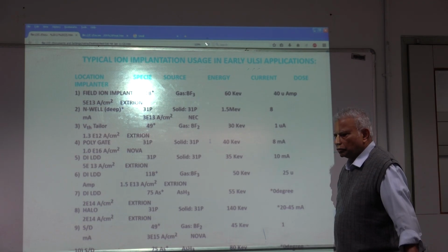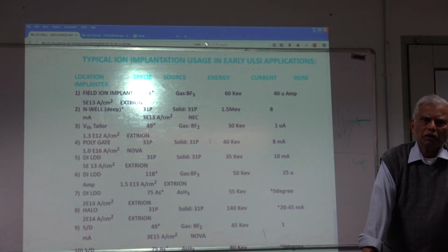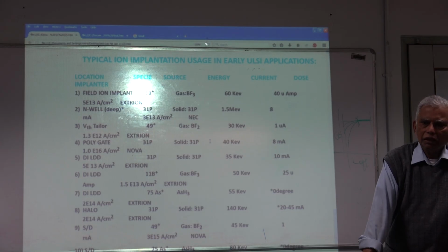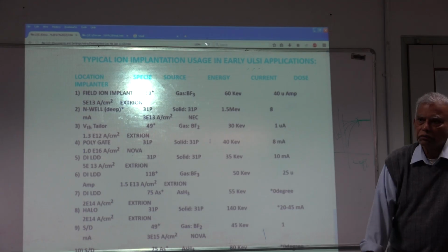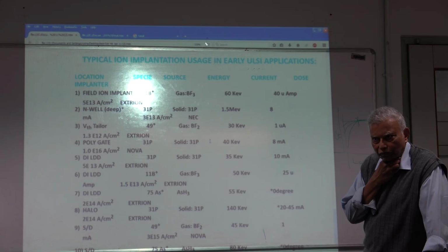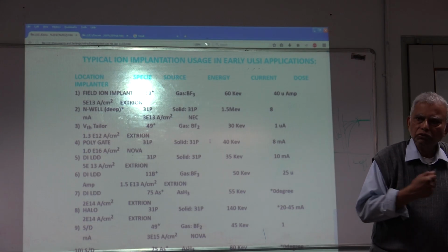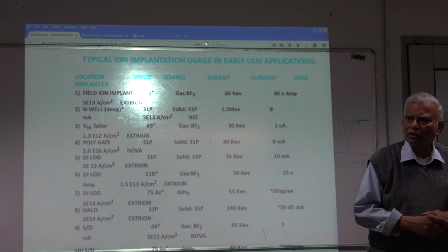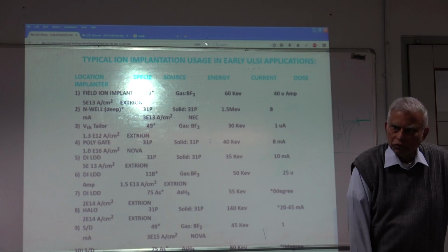So, for everything that I'll talk about with you tomorrow, assume we're using implant. We're no longer using the old way of doing diffusion. It's all implanted diffusion. And I will touch upon when you implant, especially when you implant with higher energy, we create a lot of damage, crystal damage. So we got to take care of that damage. So we need some appropriate thermal annealing so the atoms can run around all those gobbledygook that we created by implanting with so much energy, because we created a lot of defects by forcing these implanted atoms inside the body of silicon. We've got to get rid of them, otherwise we don't get good mobility, we don't get good device characteristics, all that kind of stuff.